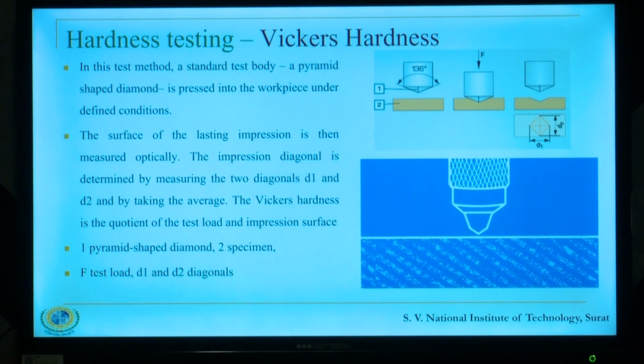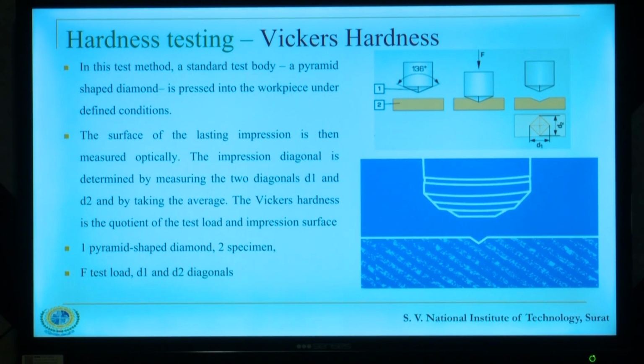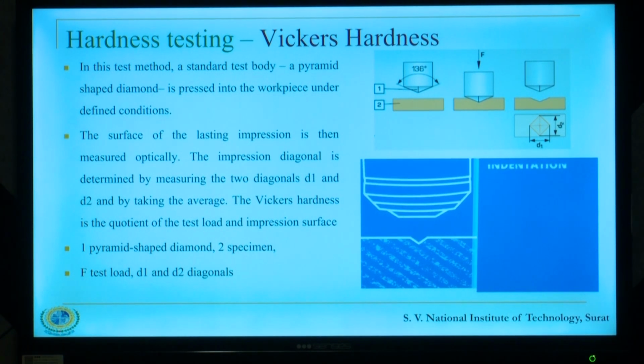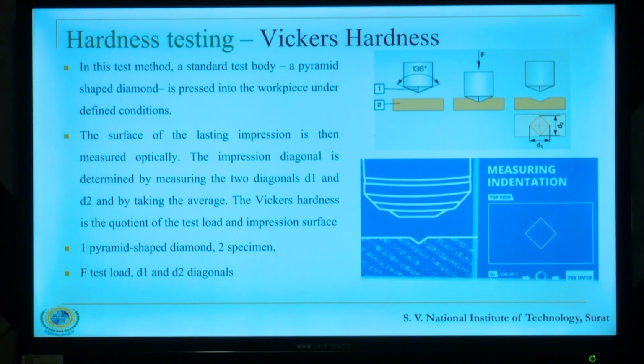In case of Vickers hardness, the indenter is replaced. It is pyramid in shape instead of a sphere. So there the diagonals of the square are measured. If it indents less, the value of D is reduced. If it is a softer material, it will indent more, and so the value of D will be more. So those 2 values are measured and calculation is done.